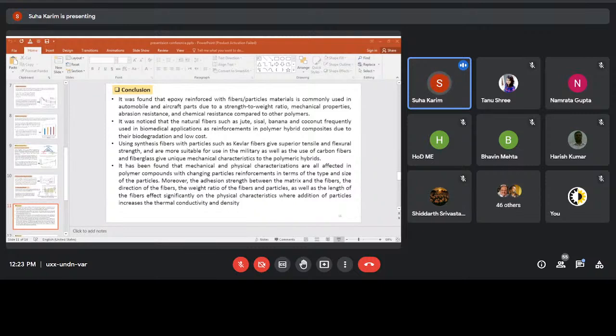Moreover, the adhesion strength between the matrix and fibers, the direction of the fiber, the weight ratio of the fiber and particle, as well as the length of the fiber, affect the physical characterizations significantly, where the addition of particles increases the thermal conductivity and density.